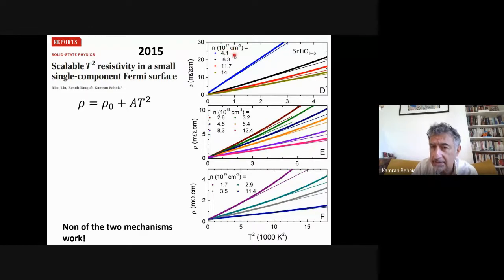This is equivalent to having 1 electron for 100,000 atoms. And then you increase the carrier density by 2 orders of magnitude. And what you see is that you have a T-square behavior. The slope becomes smaller and smaller as you go to higher and higher carrier densities.